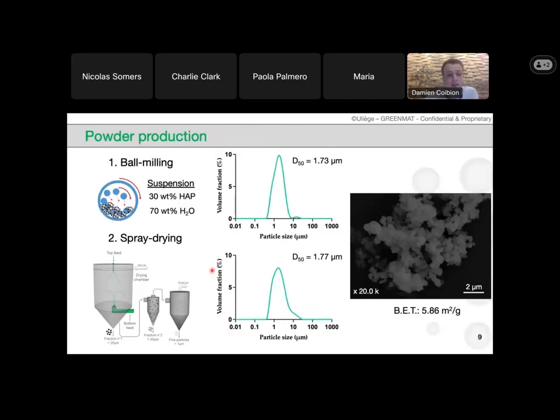So after the calcination, we have to deal with the particle size and morphology. We are doing it in 2 steps. The first one is ball milling. So we are working with a suspension where balls are hitting the hydroxyapatite particles and are going to reduce the size of the particles. So at the end of the process, we have a quite narrow distribution of size with a mean diameter of 1.7 micrometer.